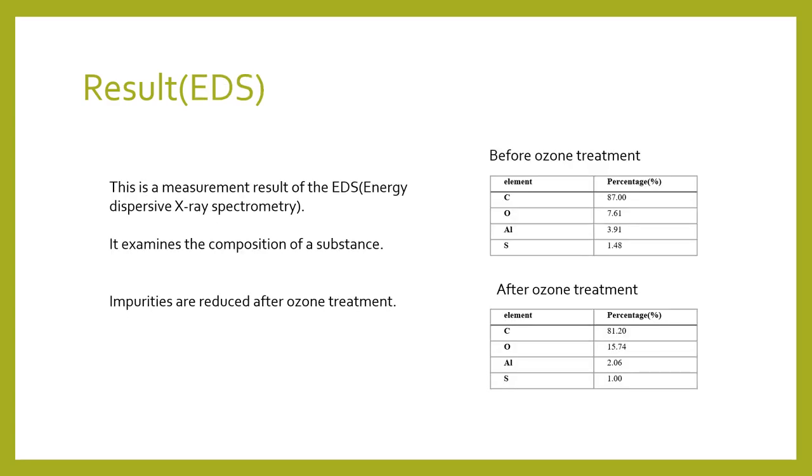This is the measurement result of the EDS. It examines the composition of a substance. This result shows that impurities are reduced after ozone treatment.